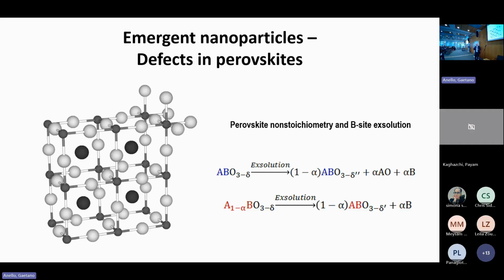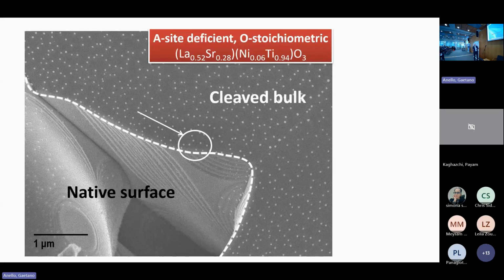Another way of looking at that is you take strontium titanate, you replace strontium with lanthanum and introduce metal cation vacancies on the A-site. Then reduce that, remove oxygen, and you now have two sites in the lattice that are empty. That destabilizes the third site, and you have, say, nickel 2+ that migrates to the surface, and it's reduced at the surface. And this is the kind of thing that you get. This is a cleaved surface, a really neat exsolution, very well supported nanoparticles. And the key thing is these can be really stable, so you can get durability from that.